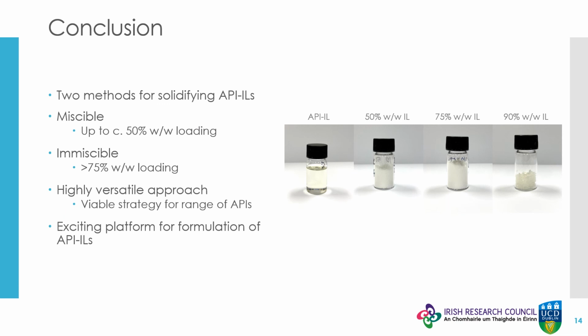Here, two methods of solidifying API-ILs using spray drying processes have been presented. Using maltodextrins as high glass transition temperature polymers, it is possible to form solid solutions of room temperature API-ILs that can be recovered from the spray drying process. This approach allows up to 50% weight-for-weight loading of the liquid drug, but unfortunately is limited by the poor solubility of the polymer in organic solvents.